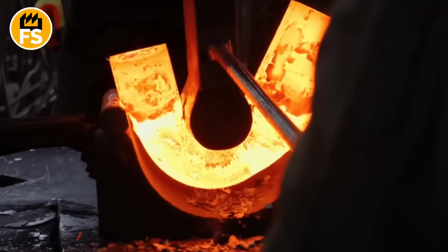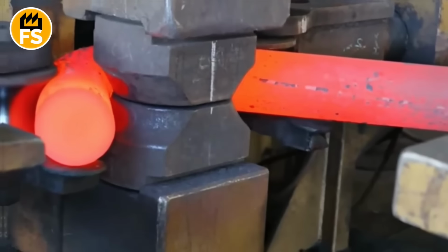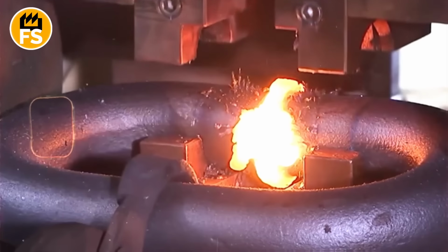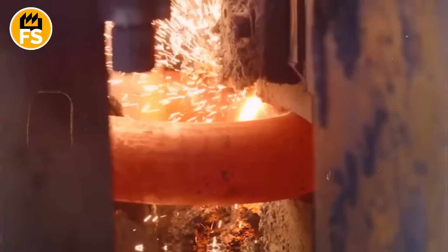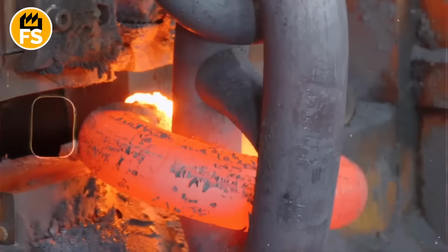When the metal heats up to a plastic state, the machine executes a sharp impact motion, compressing the parts under enormous pressure. Atoms from both pieces form shared bonds, creating a monolithic structure that's just as strong as the base metal. The weakest point of any weld is the excess molten metal that gets squeezed outward. If left behind, it becomes a source of stress concentration and microcracks.